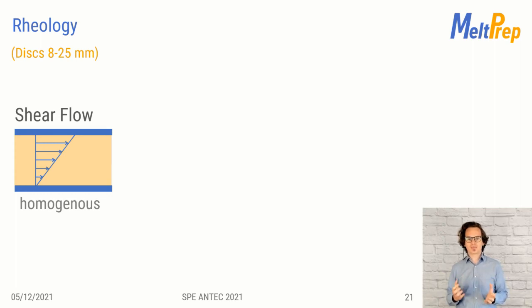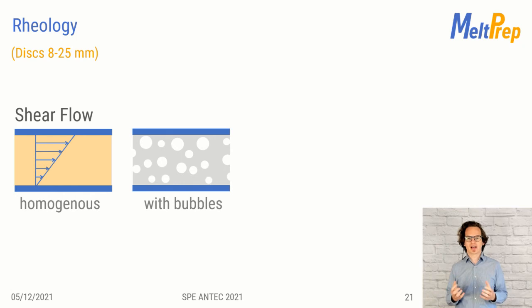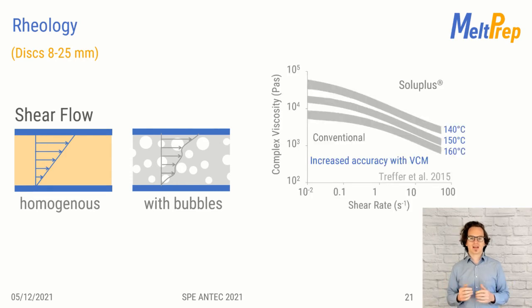But during my PhD, I realized it can only help if you receive reproducible data. During viscosity measurements, shear is applied to a molten sample and the required force is recorded. A rheometer assumes a homogeneous sample. Inhomogeneities, like bubbles or even a degraded sample, simply lead to wrong data.